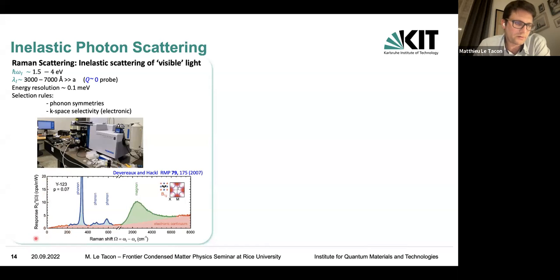So what we measure is the Raman response. That's basically the scattered photon intensity as a function of the energy loss of the photons. And we do see a continuum of excitations and some phonon lines and some magnetic excitations. So we can assess the nature of the excitation as a function of the selection rules, for instance.